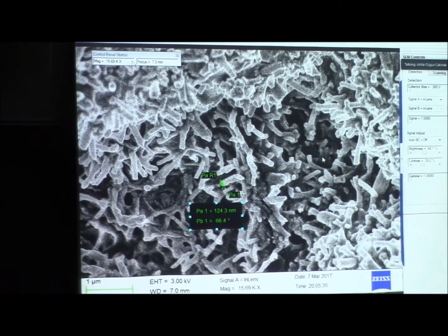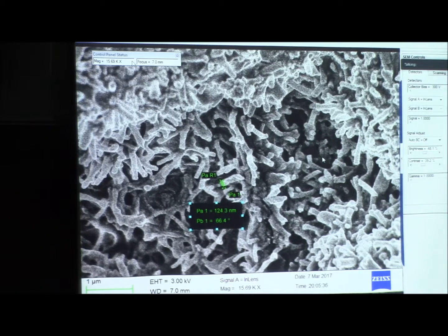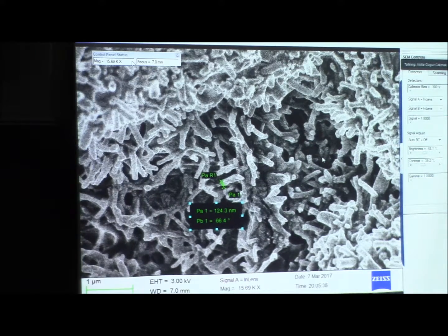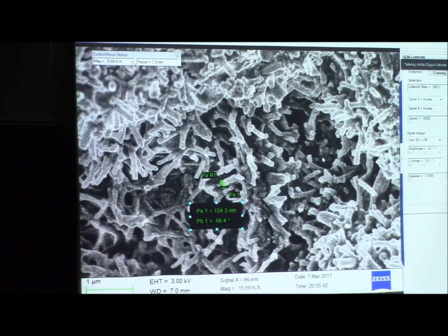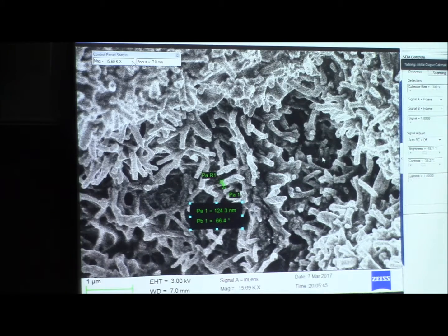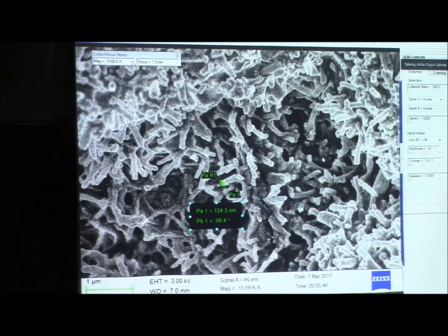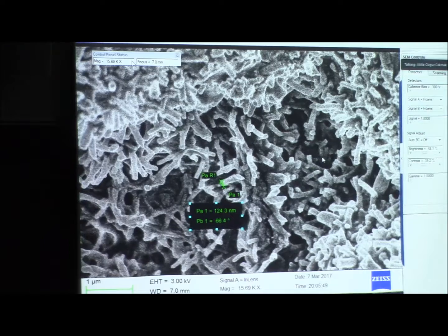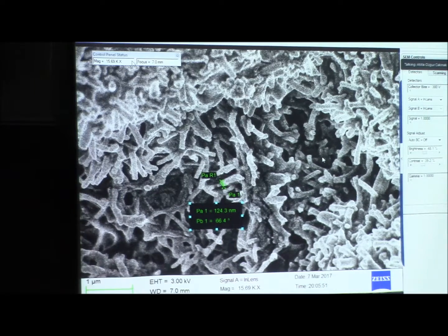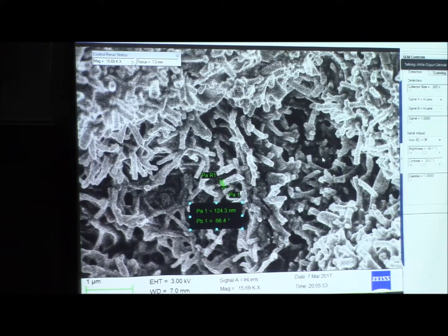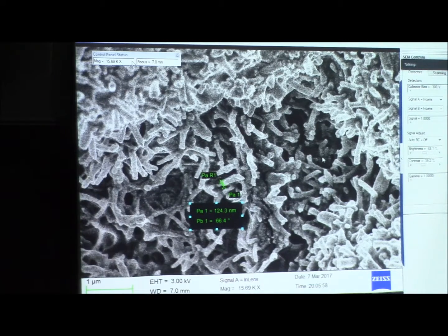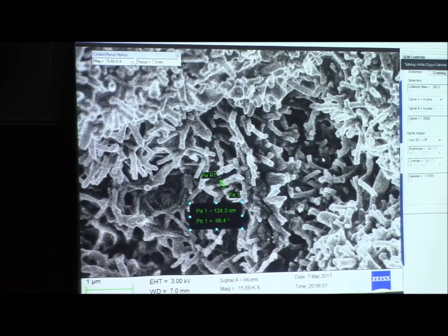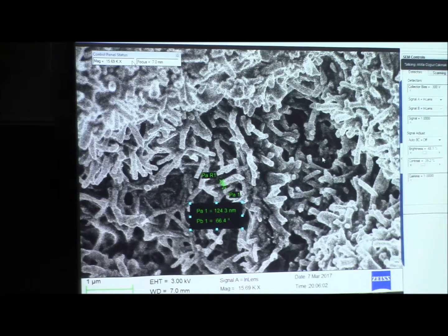Take Teflon, for example. Teflon is on these anti-adherent cooking pans, right? It's very hydrophobic, but flat Teflon's hydrophobicity is limited. It has an upper boundary. But if you could increase the roughness and get a nanofiber system like this for Teflon, then you would have a completely superhydrophobic surface.